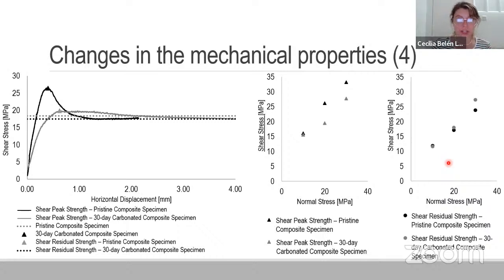So in these shear tests, what we did was test the interface defined between the wellbore cement and the rock. We were able to see that the pristine composite specimens presented a peak shear strength and a residual shear strength.